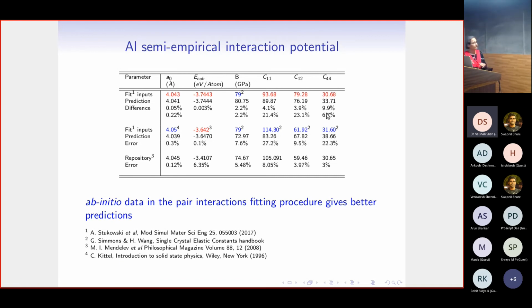And you see a second row of differences. That second reference is with respect to the experimental observation for those particular values. Any theory should be able to give a prediction that agrees with experiments, so we should be able to get the experimental results. So this is what we are looking at. We see that the elastic constants are really not being predicted that well in our current fitting procedure.